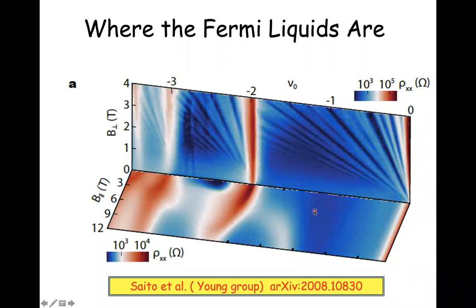In the case of magic angle twisted bilayer graphene, the Fermi surface is revealed by Shubnikov–de Haas oscillations, magnetic oscillations, most of you are familiar with. This is a usual plot, at some temperature, of resistivity as a function of carrier density, which can be tuned through this entire range, and magnetic field.